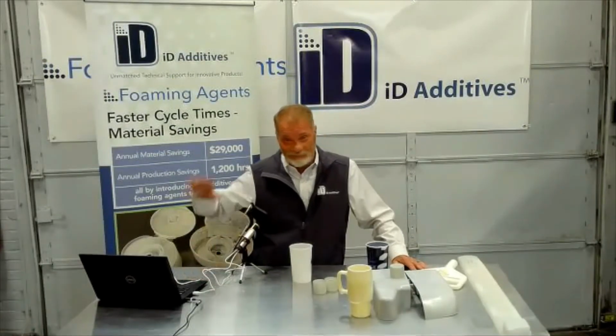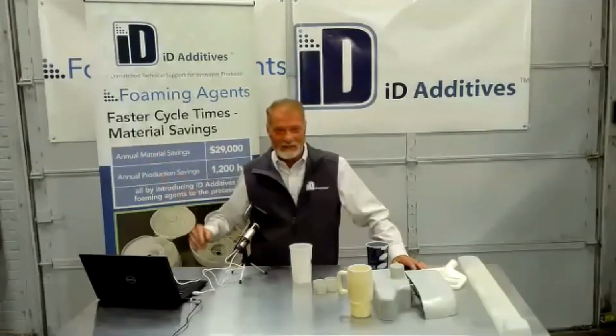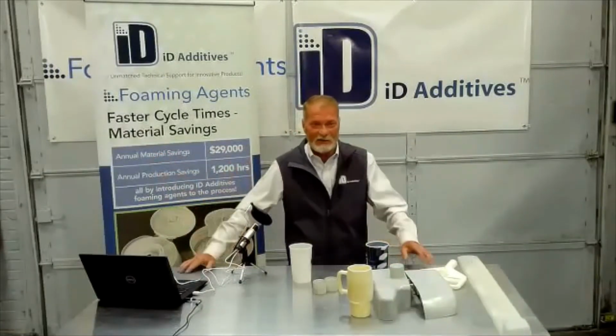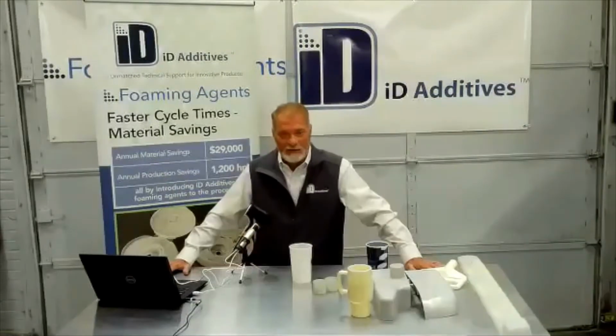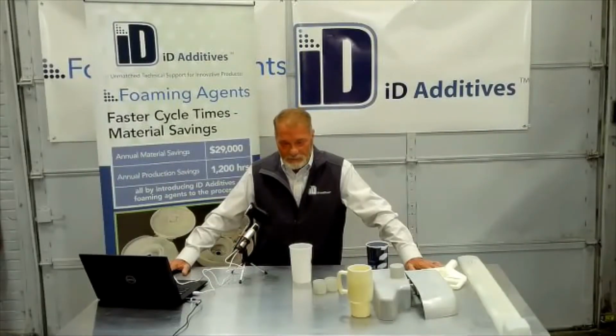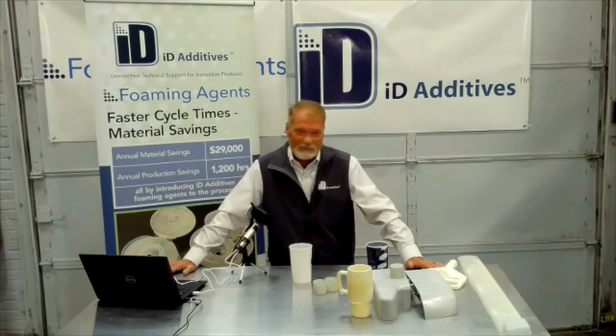I don't know how much, but it just kind of depends on how high the level of filler that you have in there. We do as high as 68% calcium, and it does wear the screw and barrel. It does, but it does open the process window for that particular part. So yeah, calcium and talc over time will wear your screw and barrel. It's rock. Can't help it. Kind of like glass. Same thing.